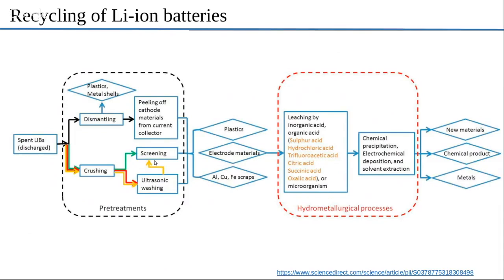aluminum, and then some of those materials will be subject to treatment, pre-treatments where they're screened. And then the ultrasonic washing separates out based on the density, based on the material, based on what can be reused or not. So once the outer jacket is taken off, then the inner part will be subject to the screening and washing.